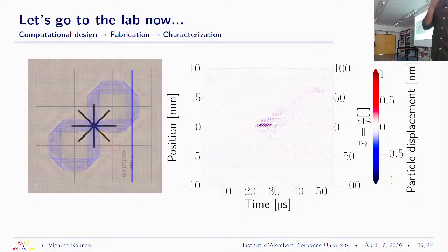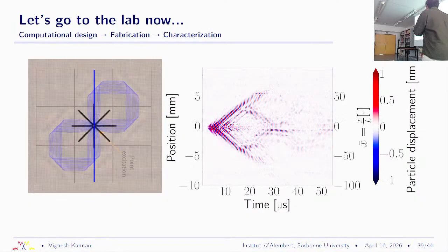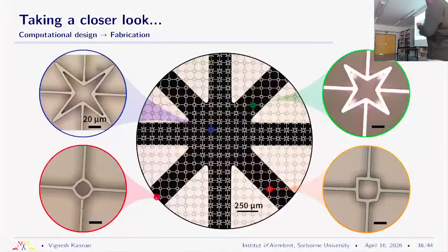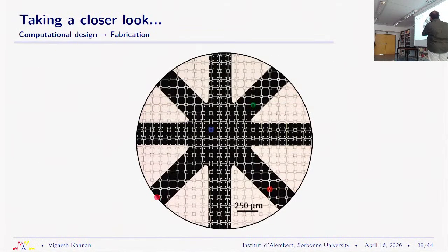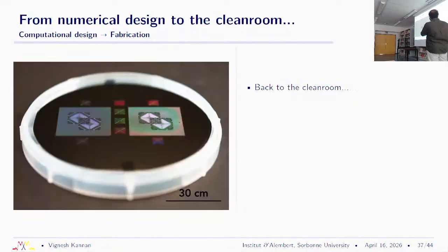But there is no flexion in their own weight, because the sample is very, very large compared to the. This is true. Now in these devices, we actually did not make the device, like I said, over the entire wafer, right? Yeah. And it's really very light, because again, you're talking about 10 micrometer beams, and because we have slender beams, your area fraction or volume fraction of material is very, very low. So it's actually a very, very thin foil of sorts.